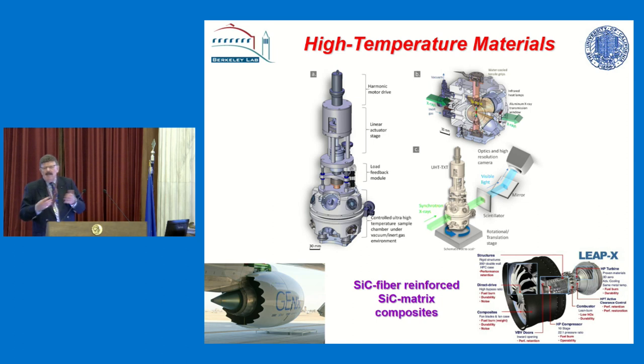I mean, if you ingest a bird into an engine, you'd shatter a ceramic engine, and that would be the end of it. But now companies like GE in particular and others are putting in ceramic composites where you reinforce the ceramic with a fiber of the same material. They use silicon carbide fibers and silicon carbide materials. The silicon carbide still breaks, but the fibers are very weakly bonded, so they act as a bridge. And so once the matrix is broken, the fibers still hold the material together, so you don't get an immediate fracture. You get a little bit like you would in a metal. You see apparent deformation, apparent ductility before fracture.